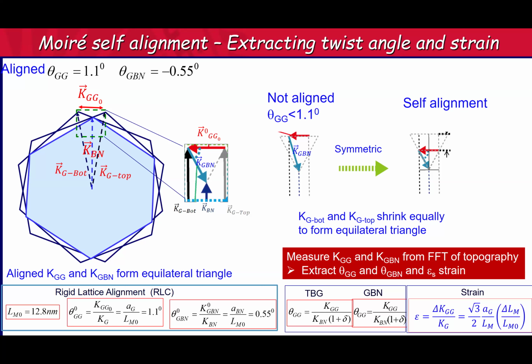Why is it that there's only one mutual size of these Moire zones that makes them exact multiples of each other? It seems like you can tune them both more or less continuously. So why can't you make them different multiples of each other? Say that again? What's the selection criterion? You said there's a single case where there's rigid lattice alignment. But in principle, the Moire unit cell seems like you can tune quite continuously. So I want 1.1, right, for theta GG to be a flat band.